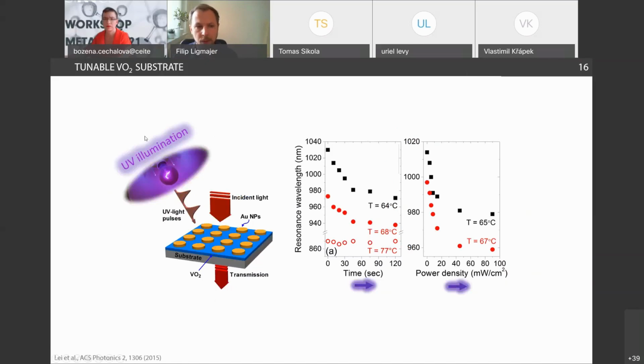What we also did in this paper was that we investigated how, by UV illumination, by UV light pulses, you can push the VO2 through the phase transition while keeping the external temperature the same. And this is also related to the volatility of the VO2 phase transition. So here you see how the resonance wavelength can be pushed to the blue side when you illuminate it with UV light pulses of different lengths or different powers.